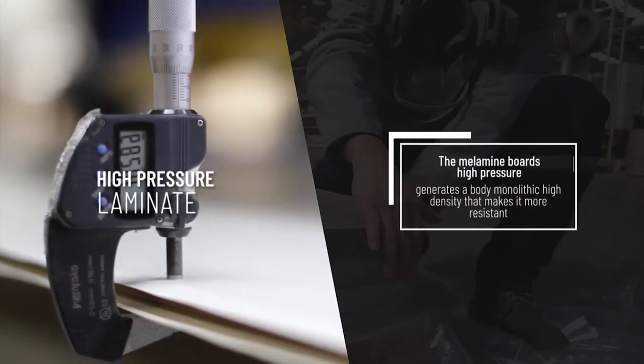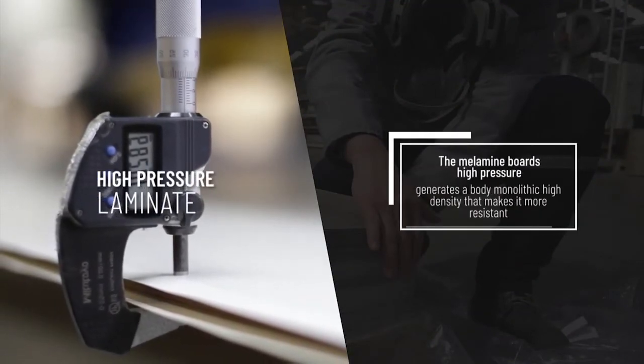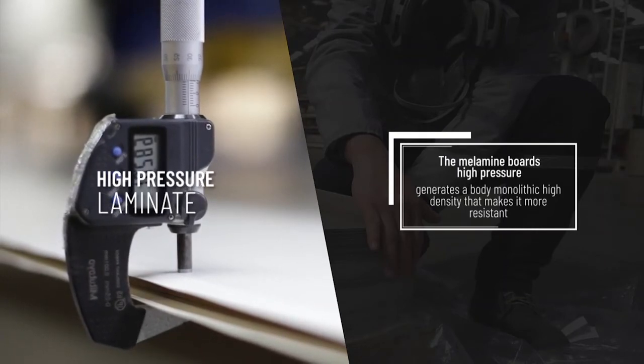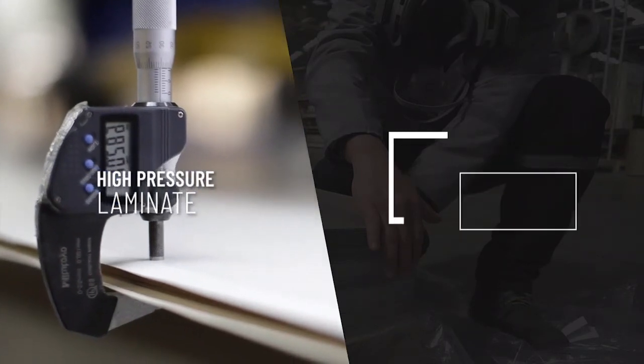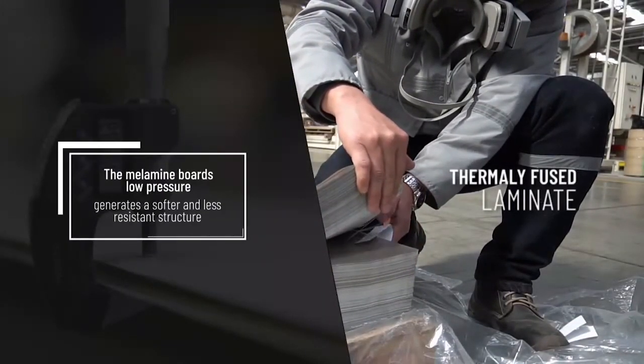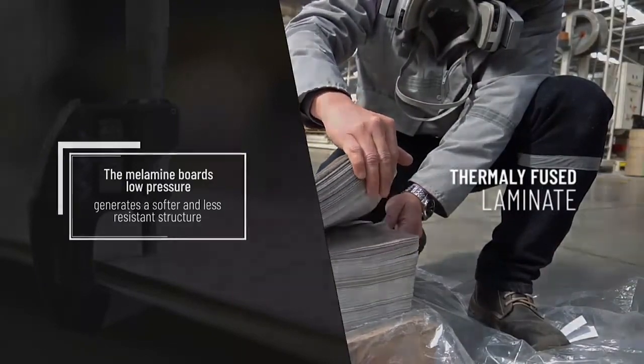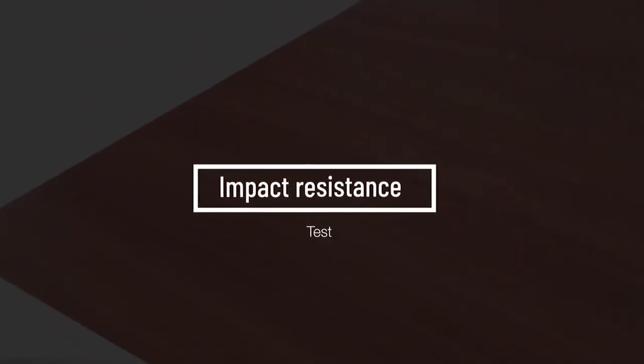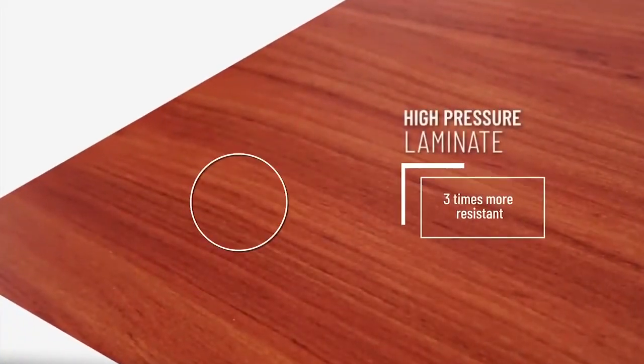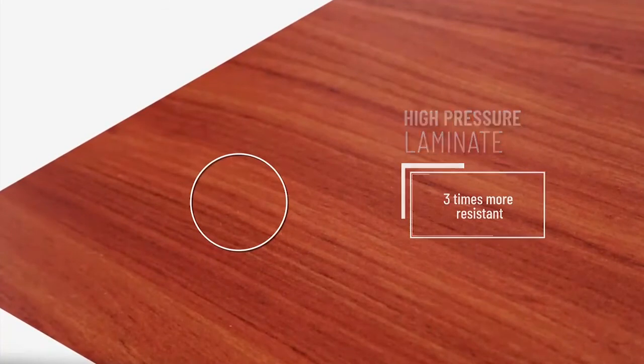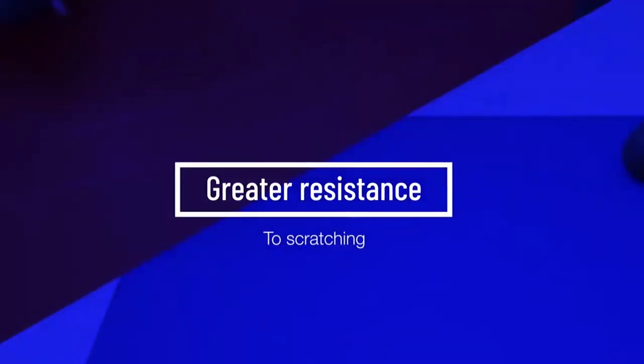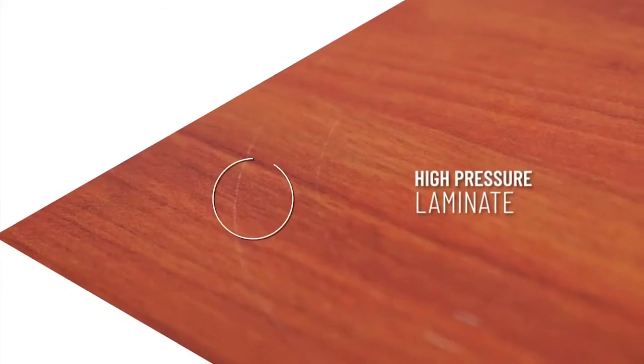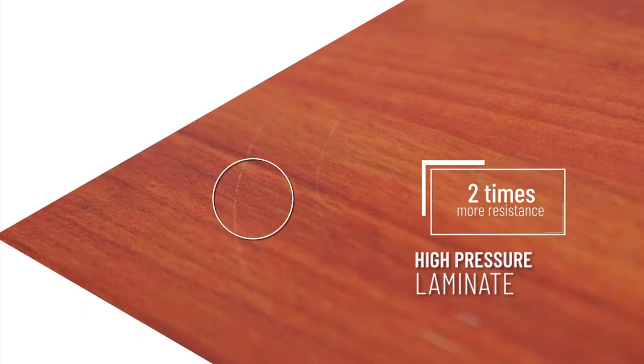HPL can be manufactured with thickness from 0.5 mm to 20 mm, which gives it different resistance to impact and allows it to be used on vertical or horizontal surfaces without problems of cracks due to impacts. TFL gives a softer and less resistant structure. HPL is 3 times more resistant to impact. HPL is twice as resistant.